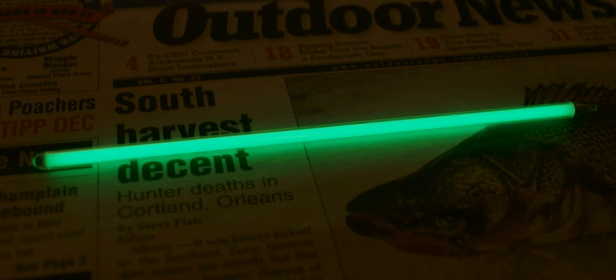The GTLSs used in watches give off a small amount of light, not enough to be seen in daylight, but enough to be visible in the dark from a distance of several meters. The average such GTLS has a useful life of 10 to 20 years. As the tritium component of the lighting is often more expensive than the rest of the watch itself, manufacturers try to use as little as possible. Being an unstable isotope with a half-life of 12.32 years, the rate of beta emissions decreases by half in that period. Additionally, phosphor degradation will cause the brightness of a tritium tube to drop by more than half in that period. The more tritium that is initially placed in the tube, the brighter it is to begin with, and the longer its useful life.